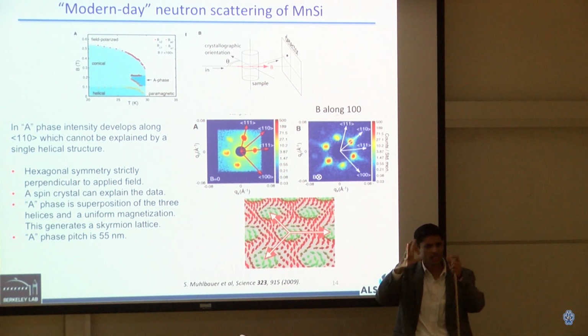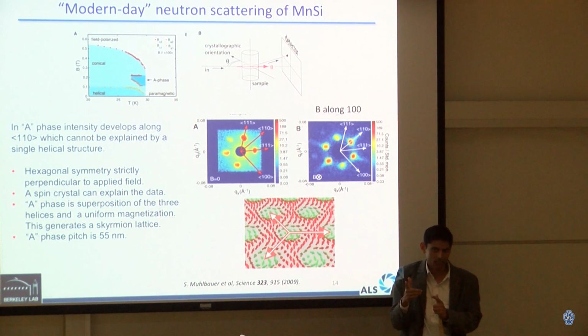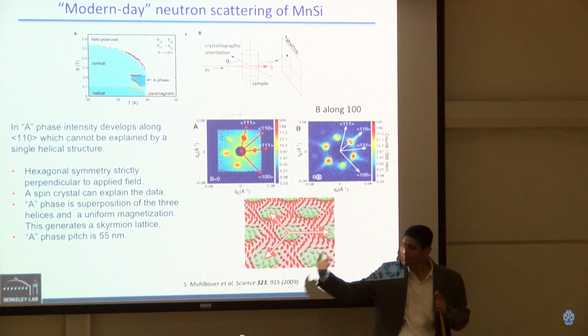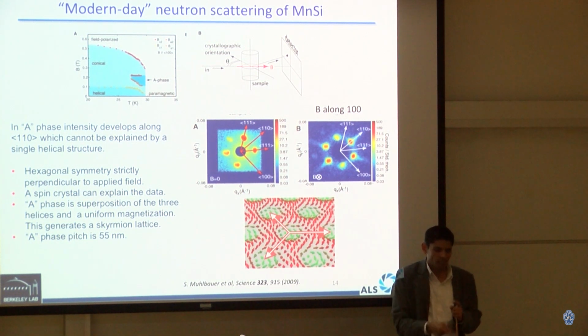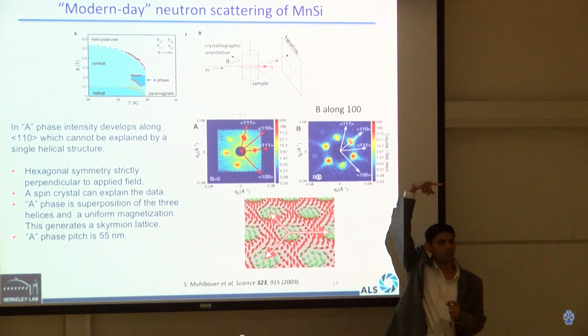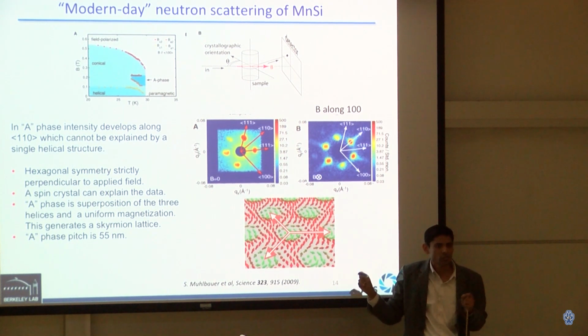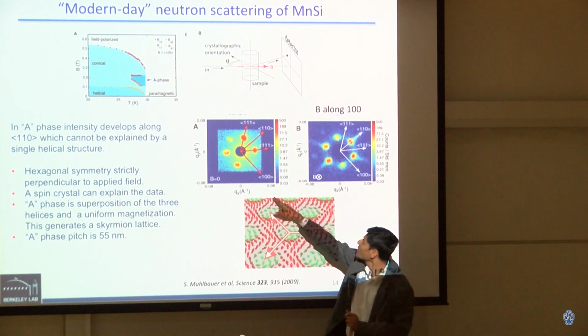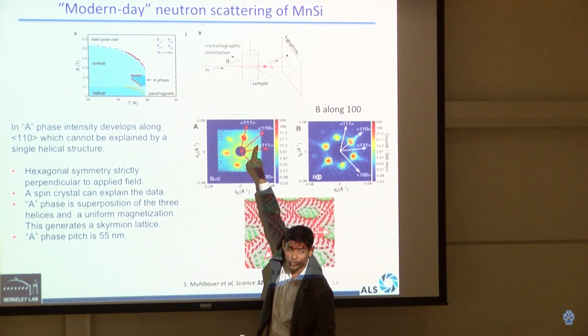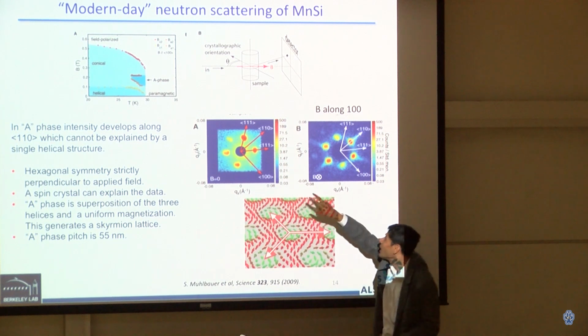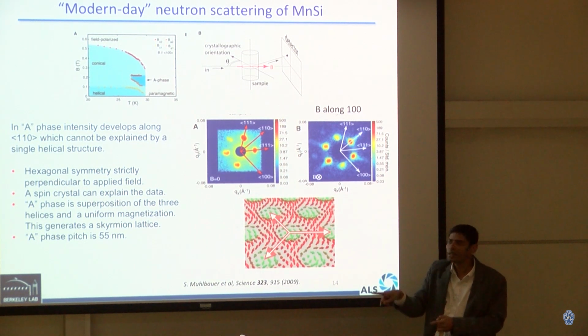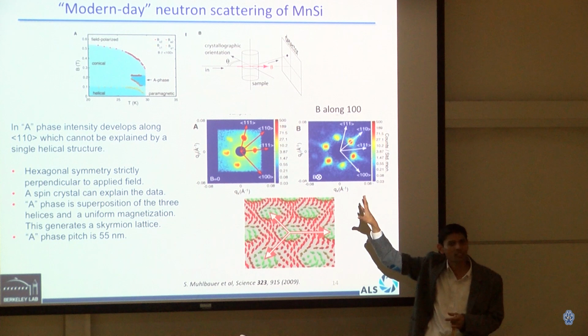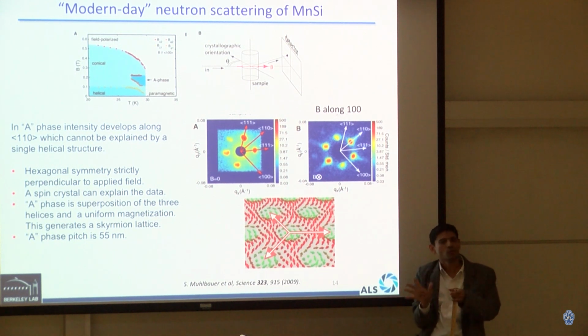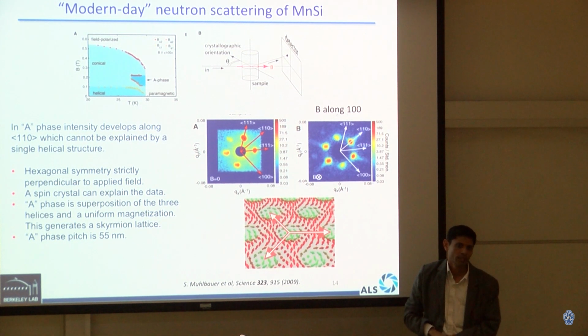So manganese silicide is a cubic structure, just like a cube. So it has X, Y, and Z, and it's a helical structure, meaning that in the X direction there is a spin helix going, in the Y direction a spin helix is going, and in the Z direction a spin helix is going, right? So each helix will give rise to 2 diffraction spots. So they see 6 diffraction spots due to the 3 helices, and then when they apply a field, the 6 diffraction spots remain 6, but they are rotated a little bit. And that's very, very bizarre. I mean, why would something just rotate out?